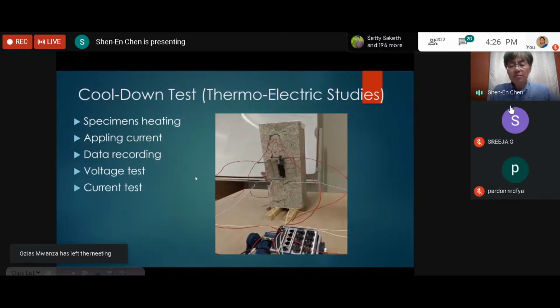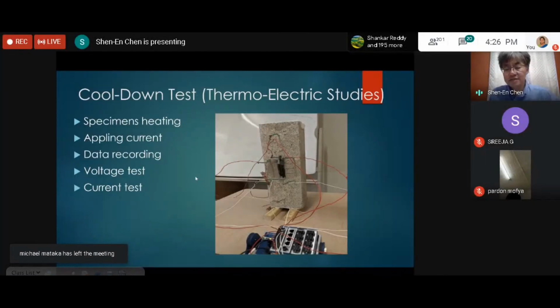And then we have another student who got interested in studying the thermal cycles of the concrete material. And so we do what we call the cool down test. We first take the specimen and then put it in the oven and heat it up to 100 degrees Celsius. And then we allow it to cool down.